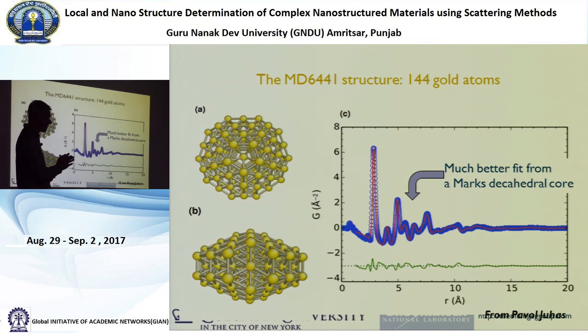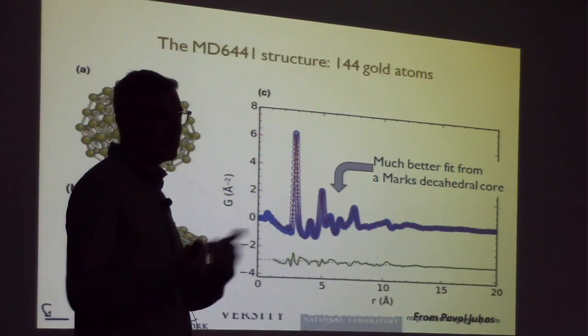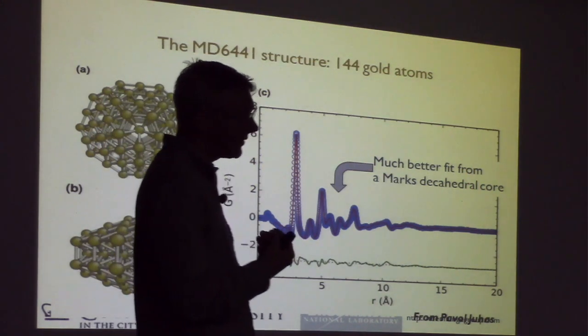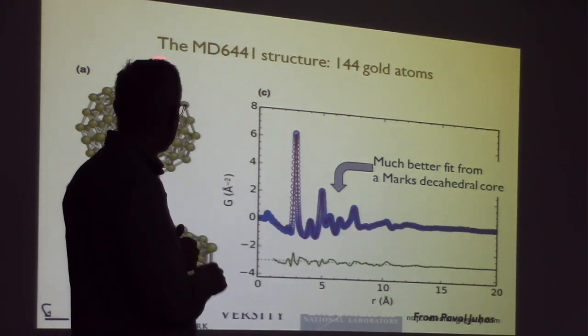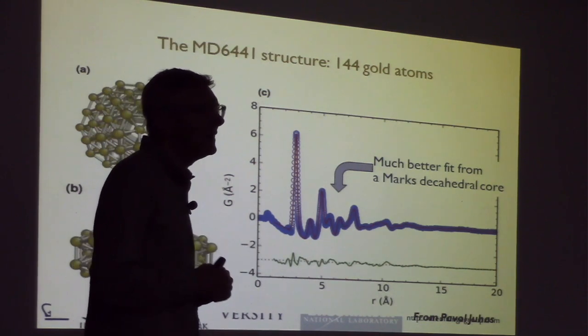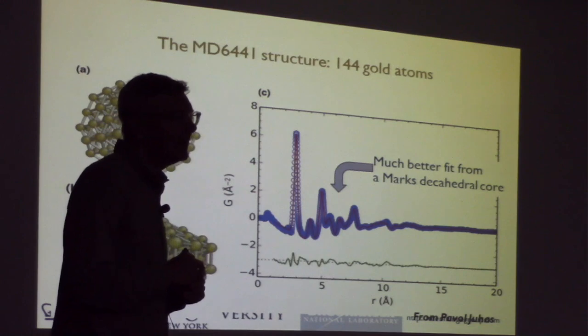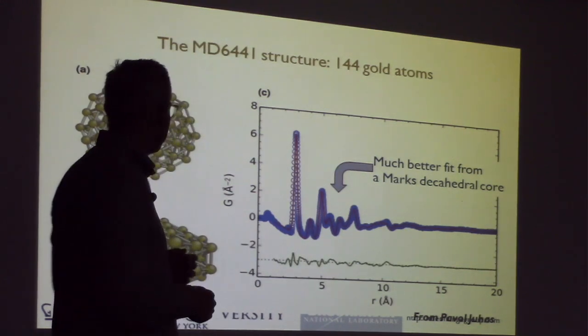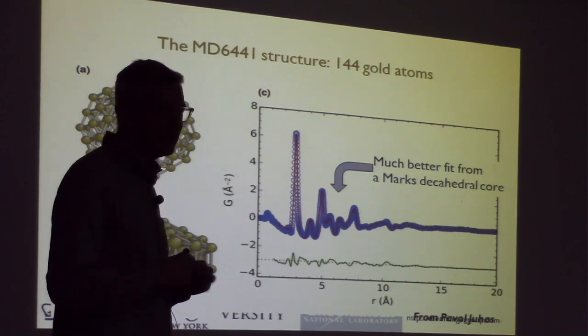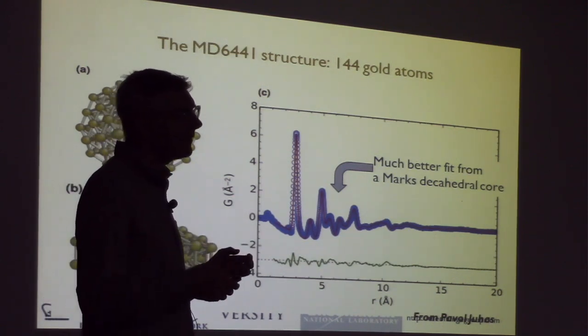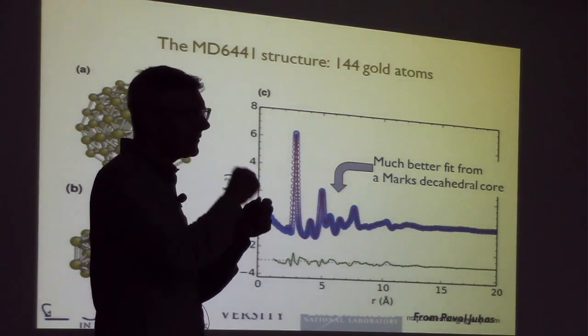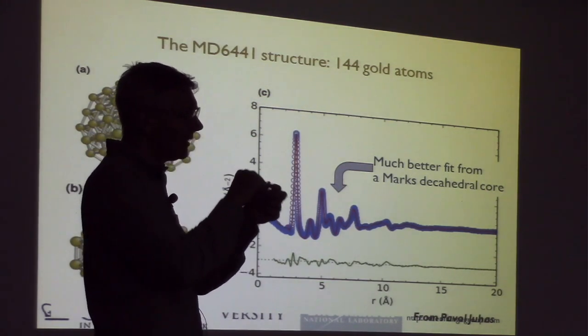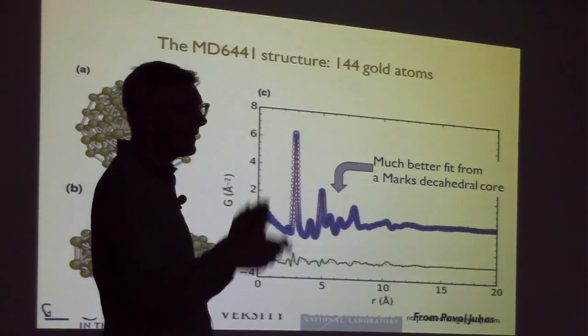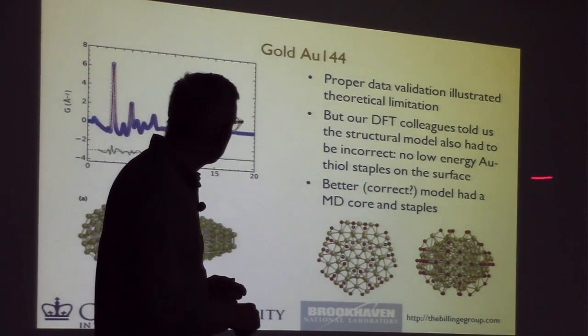Characteristic shapes which has a five-fold symmetry, so it's called a decahedron, and we get a rather good fit. So it's like, okay, the DFT got it wrong, but we showed that it's a decahedral one. So we went back to Hannu and we said, this is what we think the core looks like, and Hannu said, that can't possibly be correct, and the reason is that from a DFT perspective, this is energetically very unfavorable. And he was right. So he said that on the surface of this, you have to have these things called thiol staples. It goes gold, sulfur, gold, sulfur, gold. It's like a bridge.